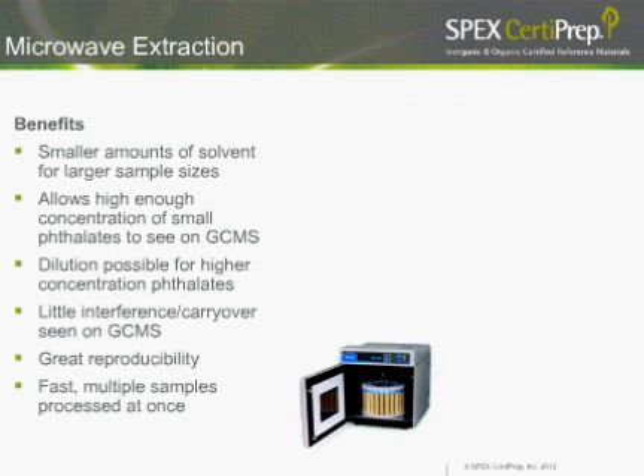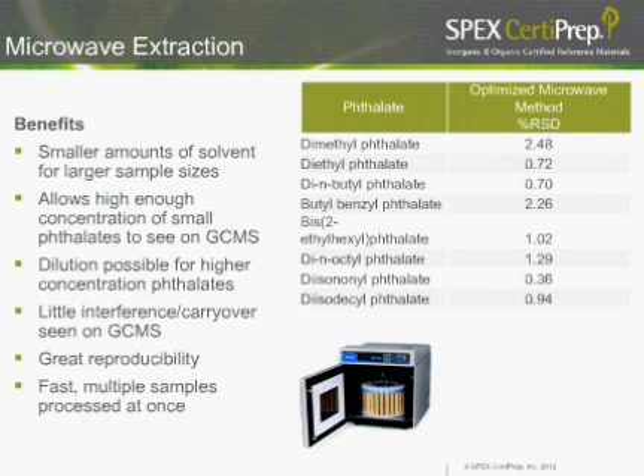And because there were multiple sample vessels, we were able to have a very high throughput. Our RSD for the microwave method was very good. You can see that the phthalates that we monitored here had anywhere from 2.5 to less than 0.4% RSD.